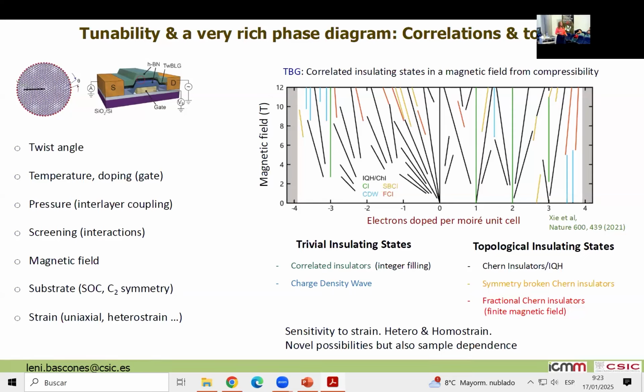One thing is also that the system is quite sensitive to strain. If you look at how the band reacts to a strain, it's amazing. And here in this system you can apply strain in two different ways. You can apply homostrain to both layers, or also heterostrain, which also happens a lot, in just one of the layers. So this is an opportunity. At present, this is still a problem, because you put these samples on the substrate, and the strain is not so well controlled yet.